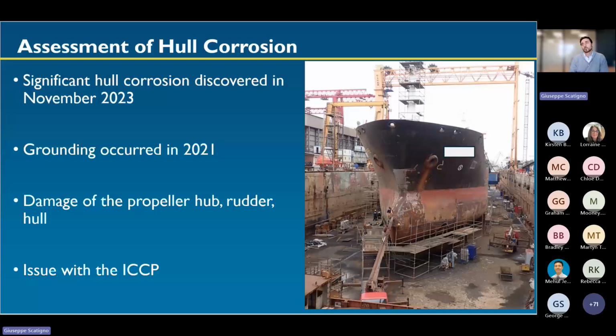And we were instructed effectively to try and understand and quantify how much of this corrosion damage could be attributed to potentially issues with the corrosion protection system that all seafaring vessels are equipped with, or to do with a specific event that the owners had discussed with the insurer, which was a grounding event that occurred in 2021. There was widespread damage found to the hull, but also to the rudder and the propeller hub, which we were asked to look into. And we were told that there had been an issue with the corrosion protection system, the ICCP.